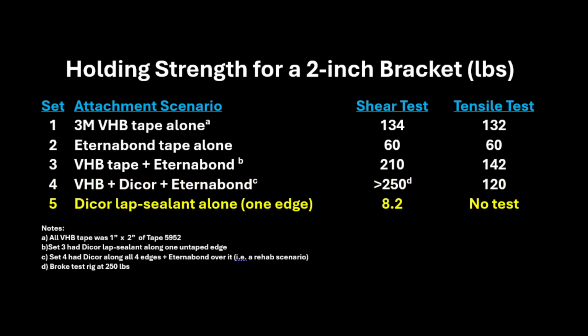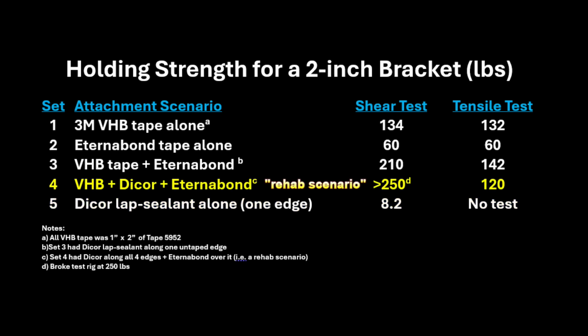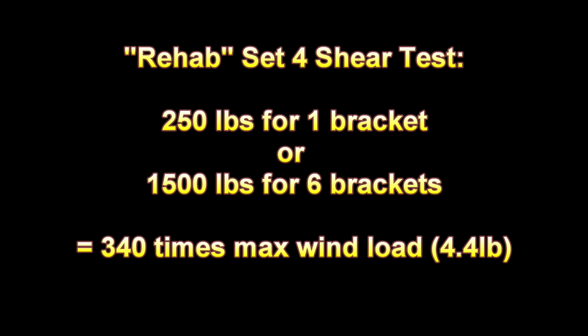Finally, test set number 5 suggests that aging Dicor lap-sealant may have added about 8 pounds per edge, or 32 pounds for all 4 edges, to test set number 4 shear strength. This rehab scenario with Eternabond over old lap-sealant was the strongest scenario at 250 pounds, or 1,500 pounds for all 6 brackets. Hundreds of times the worst case estimated wind load shear force of 4.4 pounds.